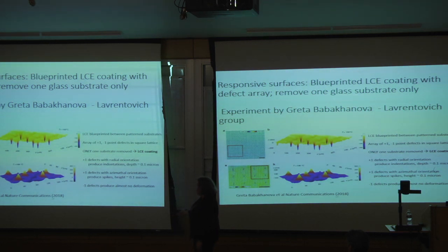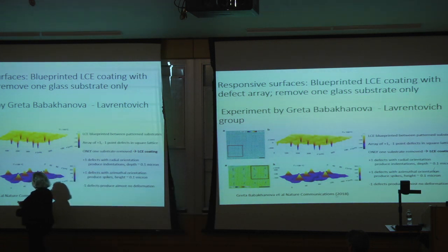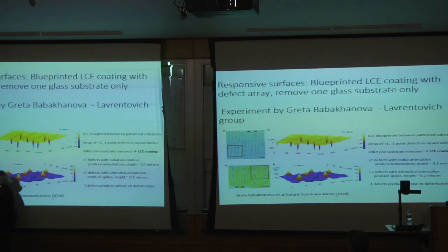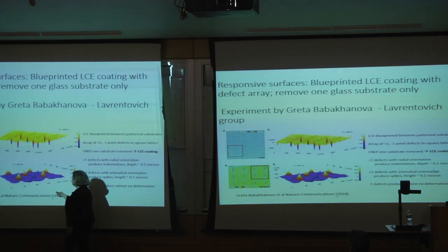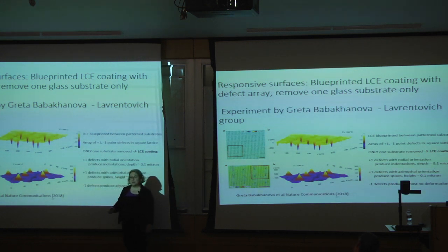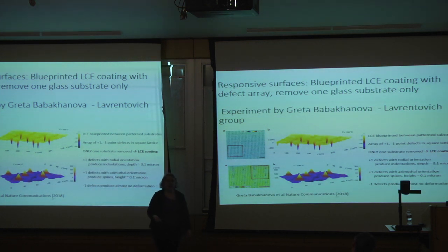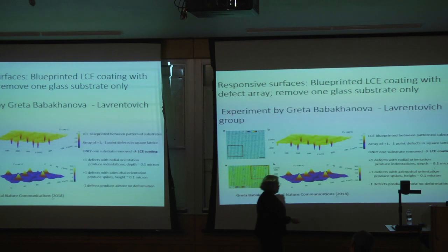So here she has an array of defects, and when she has defects that are radial, I don't know if you guys can see, but at each one of these little defect points, the nematic director points out. That's radial. Okay, and in this one, they're azimuthal. They go around like a target, like a circle. And in one case, you get dimples, and in the other one, you get spikes. So she can program shape-transforming surfaces.